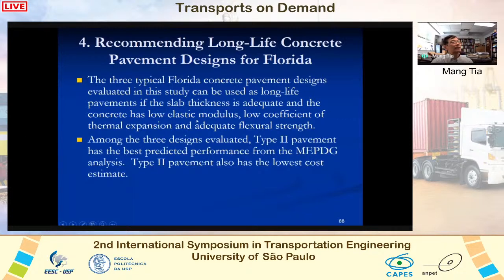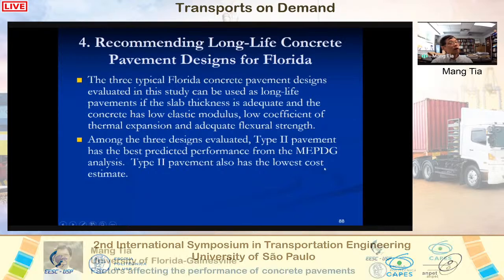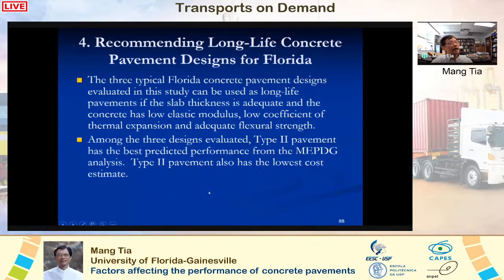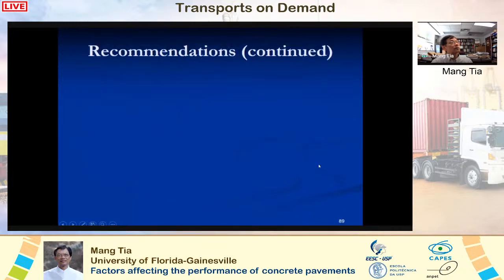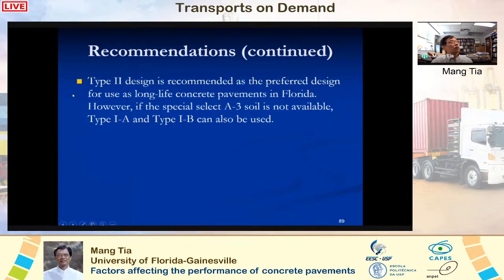Okay. If you just put in any type of concrete with enough strength, it may not work. Among the 3 designs, type 2 is the best, in terms of longest expected life and the lowest cost. And so we recommend that, if possible, use type 2 design for long life concrete pavements in Florida. But this requires the use of A3 soil, which is a good soil, permeable, good strength. But if it's not available, we can go with the type 1A or type 1B as well.